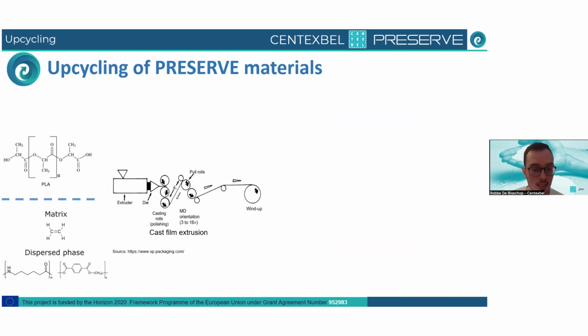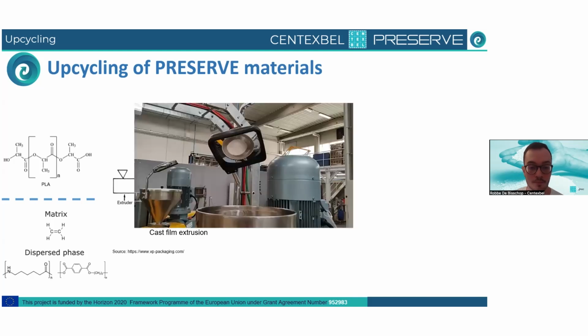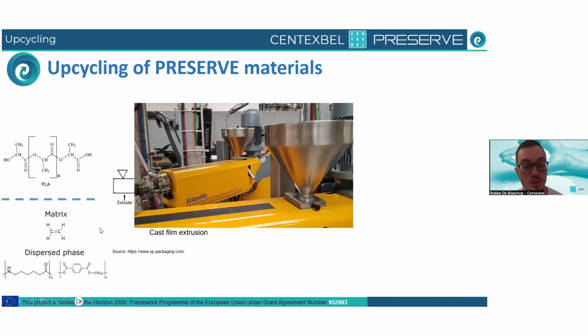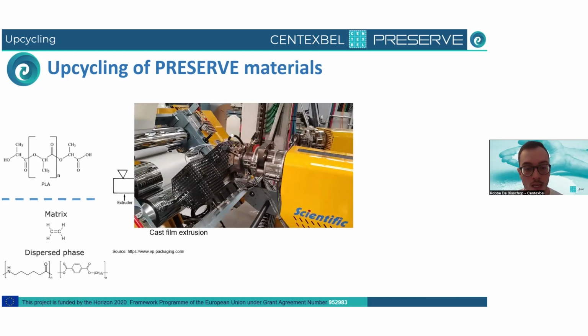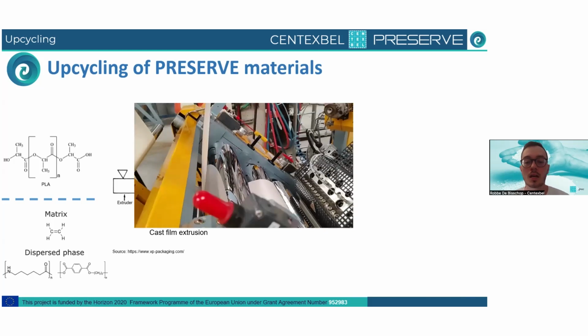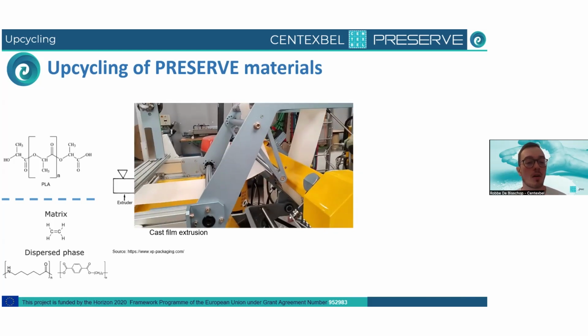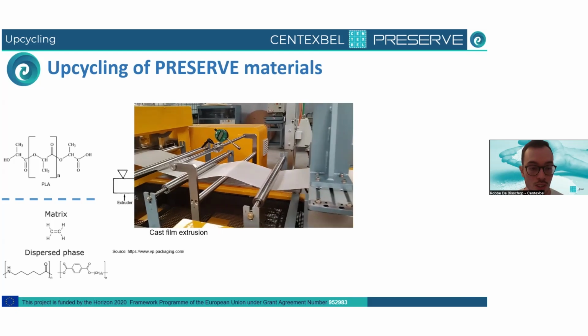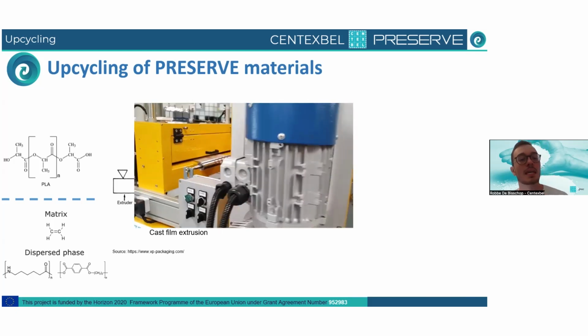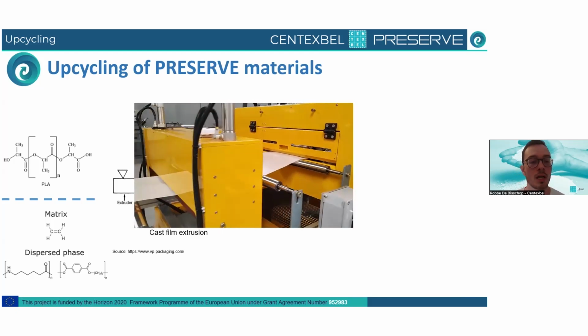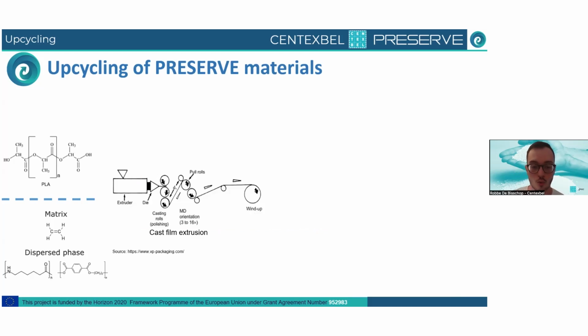We will be using this via cast film extrusion, so all of these results are done via cast film extrusion. Also, some trials have been done using filament extrusion, but I will be talking about this cast film extrusion process. Here in this small video, you can see our cast film extruder, the pilot extruder that we have at Centexbel. We can use either a very small die with one extruder or a multi-layer larger die with 3 different extruders. It's only a pilot line, so it's on a semi-industrial scale, but not just a very small lab scale, just to let you know.